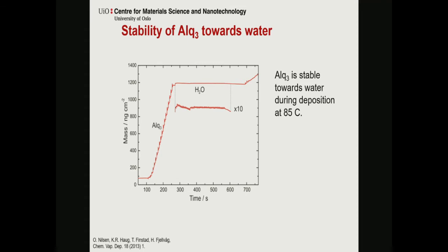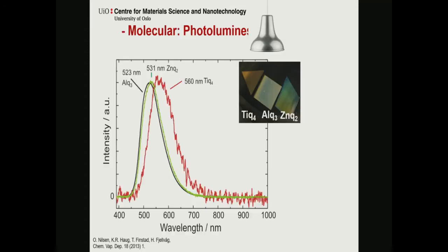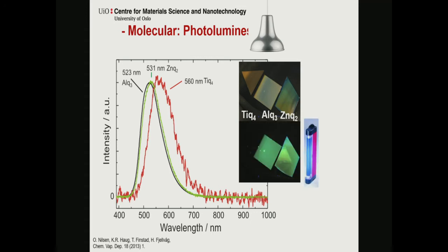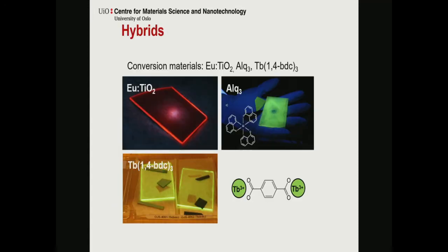The ALQ3 has been claimed to be reactive towards water. We tried to expose it and there's no mass change. But what you can say is that it recrystallizes into another crystalline structure. That it does, and that affects the luminescence. But these luminesce fairly nicely as well. So it's a nice system to play with for teasing out different sorts of excitation and luminescence.